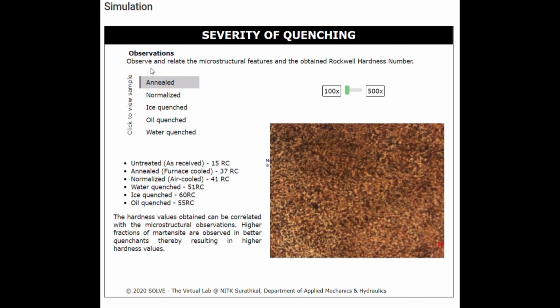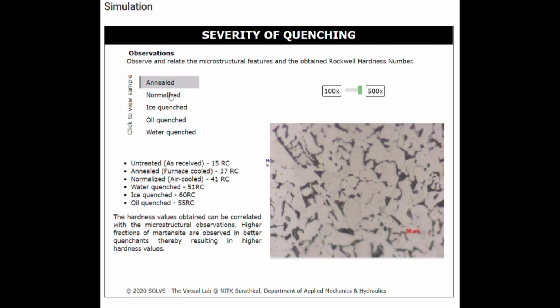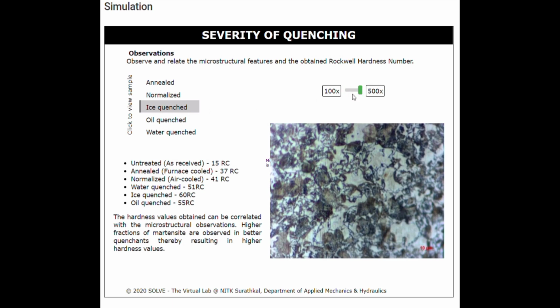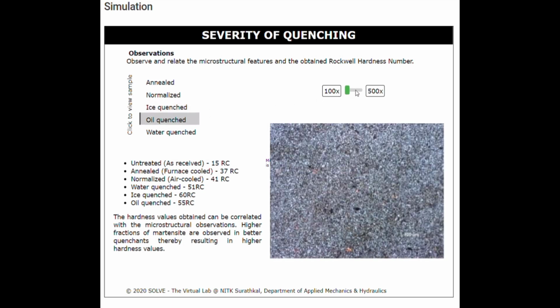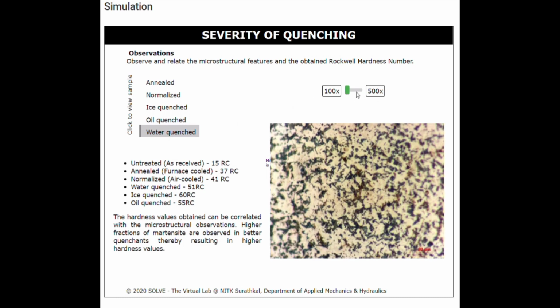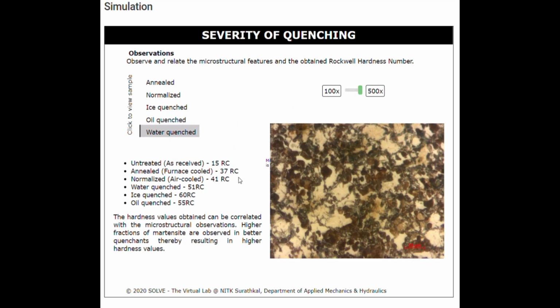From the observation: as received is 15 Rc, annealed, which is cooled in the furnace until it reaches 400 degrees Celsius, is 37 Rc, normalized 41 Rc, water quenched 51 Rc, and ice quenched is 60 Rc, oil quenched is 55 Rc.